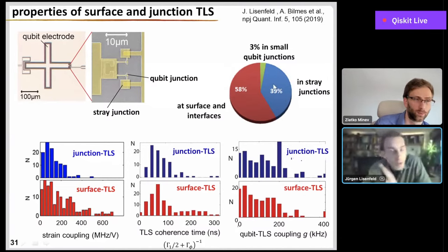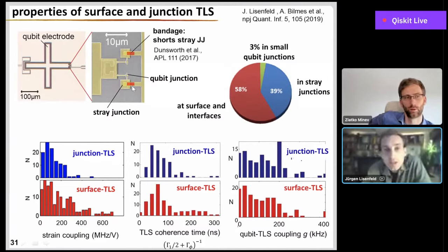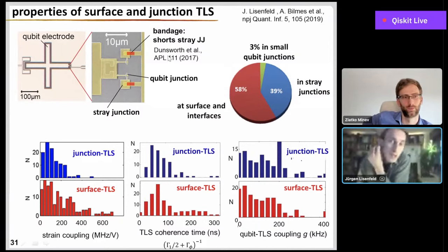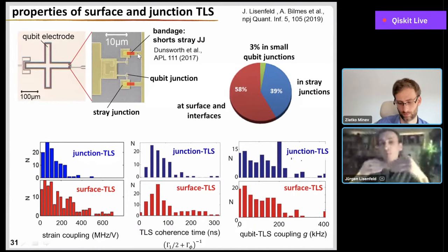And these are, of course, rather simple to get rid of. You can basically just get rid of your stray junction. There's a technique for this called bandaging. So you just put another small layer of aluminum film there to short this stray junction. And then you automatically get 40% less dielectric loss in your qubits.